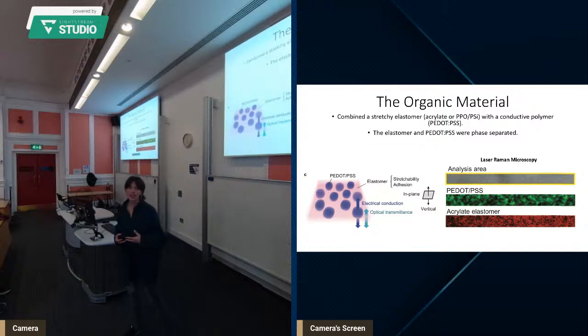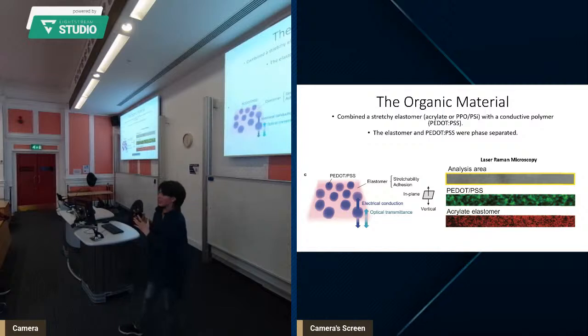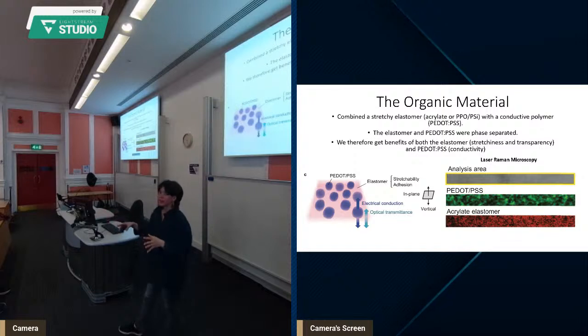So what that means is that if you look at the image to the left, you can see that PEDOT PSS actually agglomerates. And the elastomer forms the kind of liquid surrounding the PEDOT PSS agglomerates. So this is actually beneficial. I'll explain why these agglomerates are beneficial in a moment. But we can see that when you have these PEDOT PSS agglomerates with an overall elastomer area, we actually get the benefits of both the stretchiness and the conductivity.